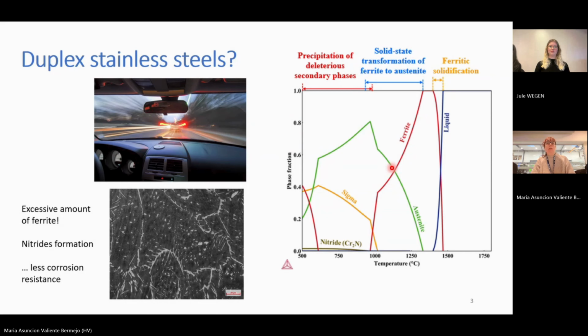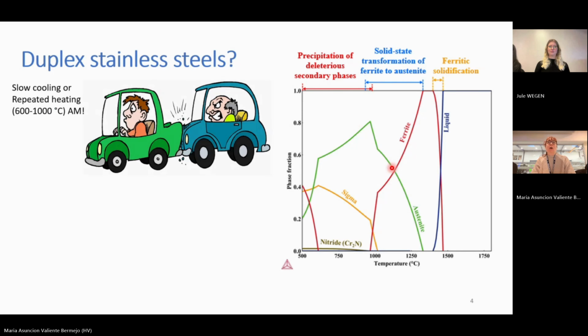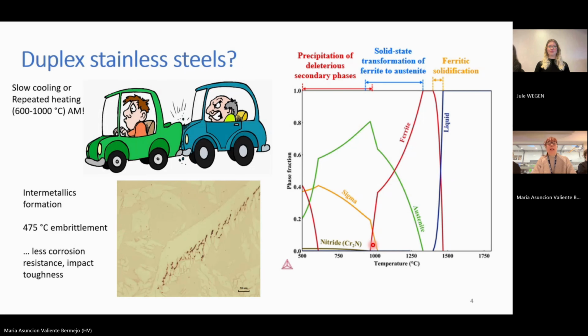But what happens when we have the opposite case, when we have very slow cooling, or, as in the case of additive manufacturing, repeated heating? Then we end up forming this undesirable phase, the sigma phase. So ferrite decomposes into chromium-rich and moly-rich areas, and it segregates and forms these intermetallics. That can end up with embrittlement, less corrosion resistance, and less impact toughness. So this is very detrimental, especially for mechanical properties.